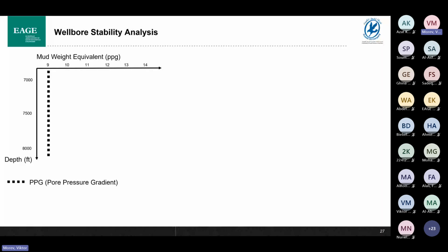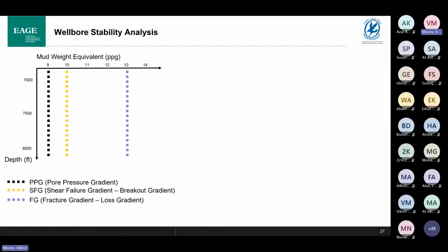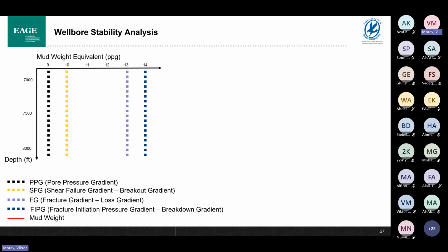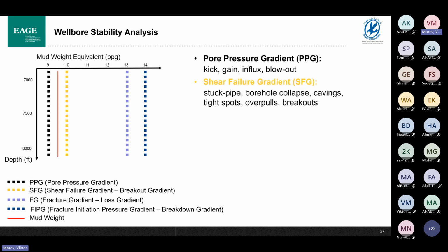So here on the slide, on the plot, you see the pore pressure gradient. You see the shear failure gradient, or in other words, breakout gradient. We also have the fracture gradient, loss gradient, and the fracture initiation pressure gradient, breakdown gradient. So let's consider case by case what will happen if I drill the well with some particular mud weight. So when my mud weight during the drilling is lower than the pore pressure gradient, I'm getting such events as kick, gain, influx, or in the worst case scenario, blowout. When I decide to increase my mud weight to be higher than the pore pressure gradient, but still lower than the shear failure gradient, I'm getting such events as stuck pipe, borehole collapse, cavings, tight spots, overpulls, and breakouts, which we see on the microimager.